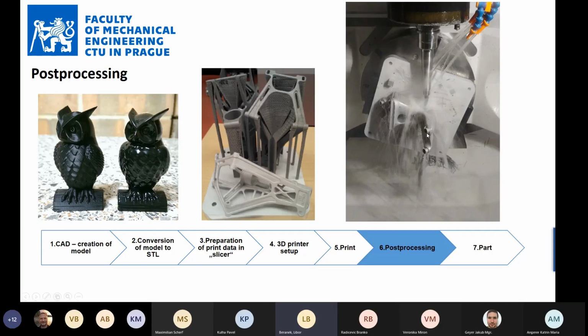So you can see that there are a lot of features here which are used just for measuring inside the production machine, inside the CNC machine, or inside the CMM, coordinate measuring machine, where you can get some kind of corrections, because you have to understand you cannot program the part using CAD data, because the CAD data is not valid anymore.